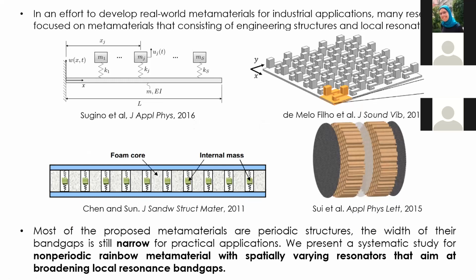Besides these, in an effort to develop real world metamaterials for industry applications, many researchers have also developed metamaterials with engineering structures. For example, metamaterials composed of beams with resonators, plates with resonators, and the widely applied sandwich structures with resonators, like this. Most of the proposed metamaterials are periodic structures. The width of the band gaps is very narrow for practical application. The worst case is that the lower the band gap frequency is, the narrower the bandwidth is. That's why we developed non-periodic rainbow metamaterials with spatially varying resonators that aim at broadening local resonance band gaps.